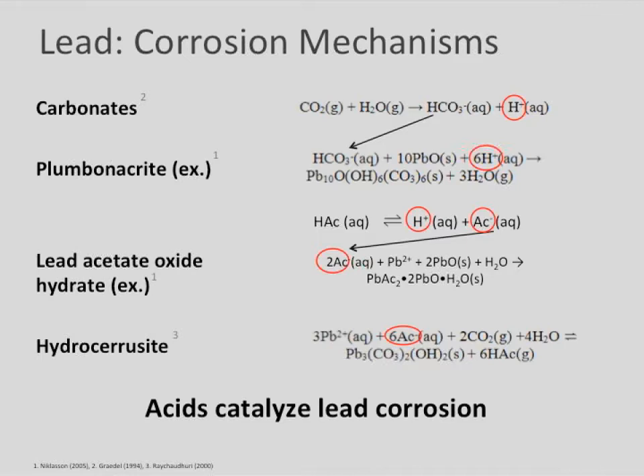That carbonate with a lot of acid in the presence of lead oxide, which we've already seen from the previous slide, can form—just in the presence of oxygen—plumbonacrite, which we saw a lot of on these coupons. And if you have an organic acid like acetic acid, that can dissociate, forming protons that feed into this reaction. In addition, the acetate anion can then be used to help form lead acetate.